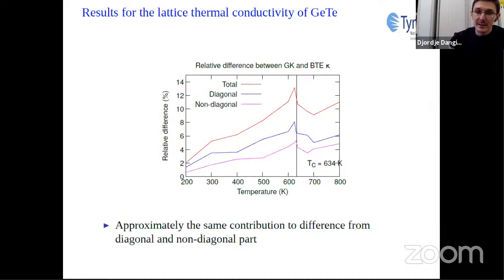If we split this difference into parts that come from the diagonal and non-diagonal part of the lattice thermal conductivity, we can see that they are roughly equal in germanium telluride. One has to keep in mind that germanium telluride is a fairly simple material with only 2 atoms per unit cell. We expect that in more complex crystals the non-diagonal part will be much more prominent.